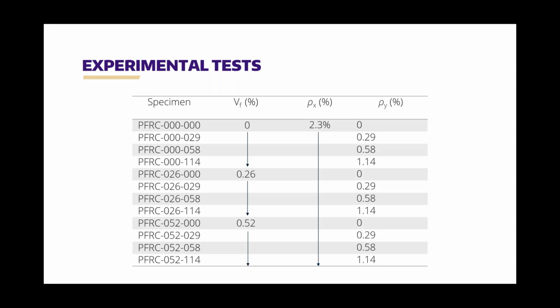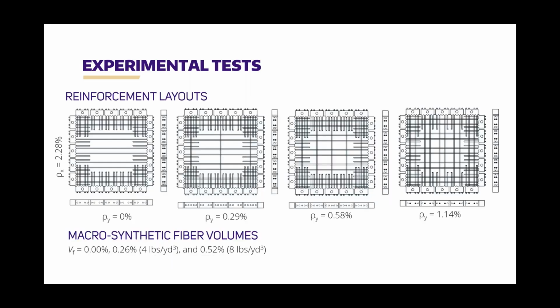So we have a test matrix. We have a series of panels here. The panels have different volume fractions of fiber. So that's the first column there, VF: 0, 0.26, and 0.52. Those correspond to about a typical dosage ratio recommended by the manufacturer and the maximum dosage recommended by the manufacturer. You can see that the longitudinal reinforcement ratio, rho X, is constant throughout the panels, and then we're varying the amount of transverse reinforcement, rho Y.